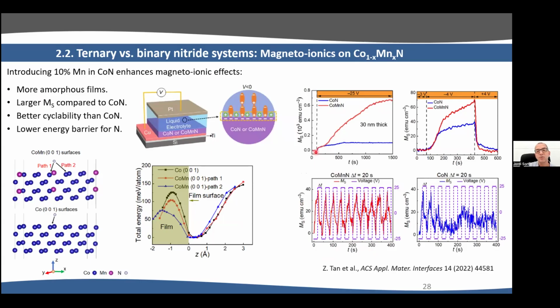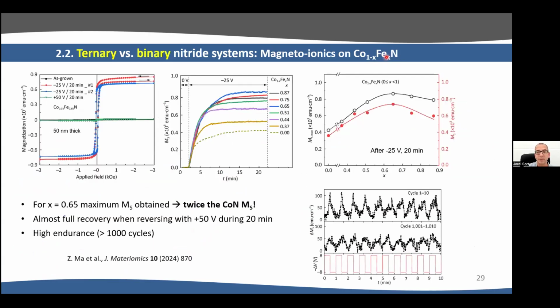And one of the reasons why it's better with manganese addition is that the energy barrier to incorporate nitrogen in cobalt manganese is lower than for cobalt. So you can see here with cobalt, the energy difference between this maximum and the minimum is larger than compared to cobalt manganese, which are the red or the blue curves. But manganese itself is non-magnetic. So we thought maybe adding, instead of manganese, adding iron could be even a better choice.